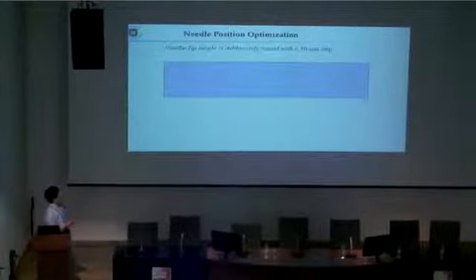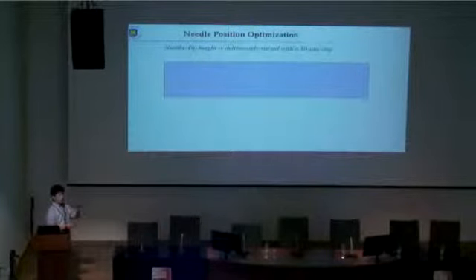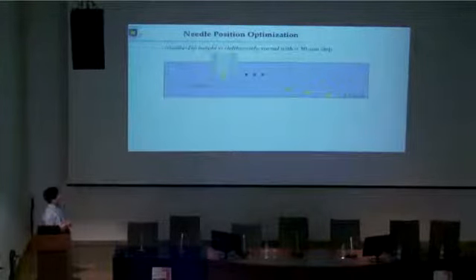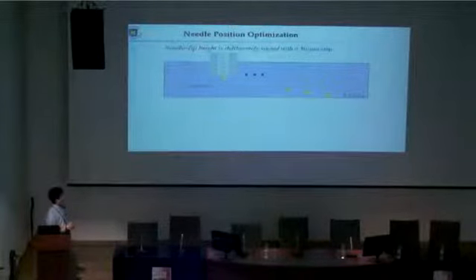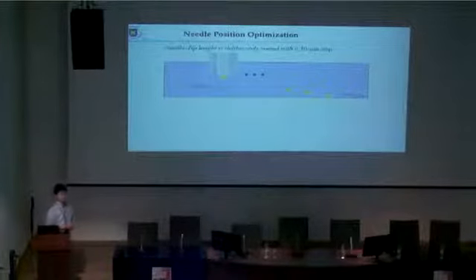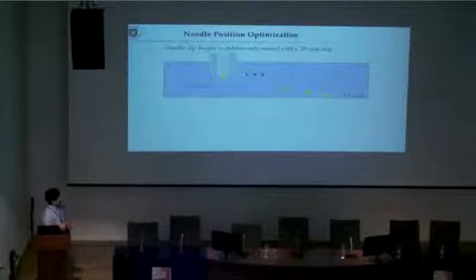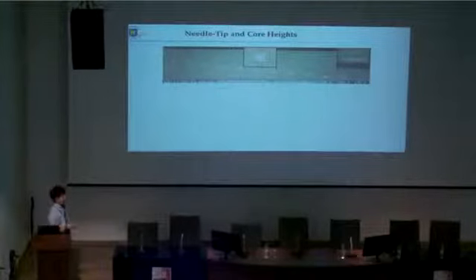So we evaluated the needle tip height and the core position in detail. In this experiment, we deliberately varied the needle tip height from the substrate in this way. At the initial point, the height was preset to 50 micron higher than the substrate, and with a 30 micron step, the needle tip height is widely varied. And here is the result.